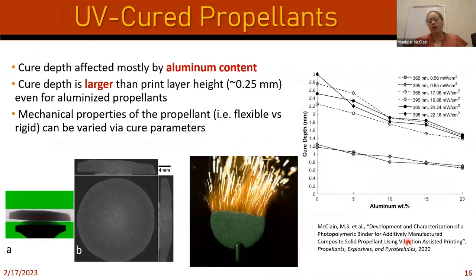And then finally, we moved on to testing the actual propellant mixture. So now we actually looked at, okay, what happens when you have 85% of these particles? So you could either have some content of aluminum up to 20% or just all ammonium perchlorate. And then here, this is where we measured the cure depth of that propellant. So what we did was the same type of study, but we were focused more on the depth that it cured at.